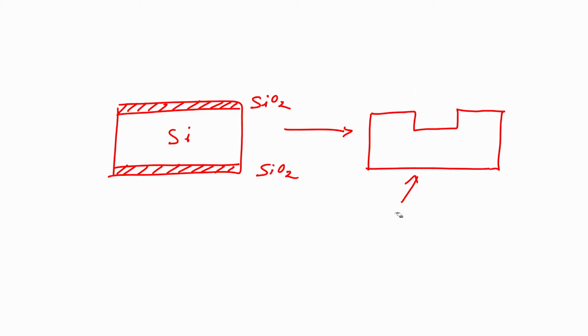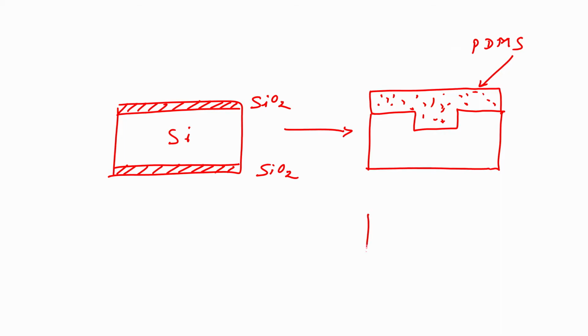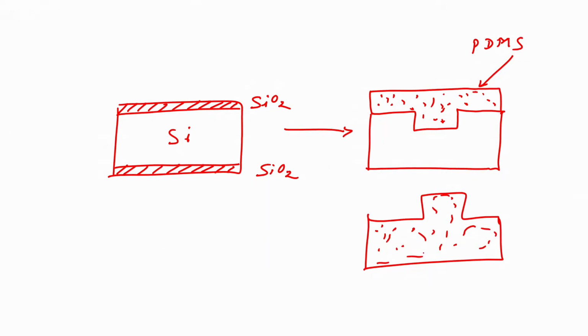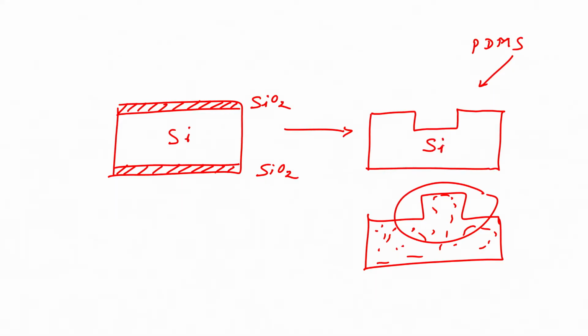So, we will have a mold on which I spin coat or pour PDMS, this is my PDMS, and cure it. After curing, I can strip it off. What will I have? I will have a PDMS structure like this, right. After I strip it off, I can get back my mold, and I have already patterned my PDMS using this particular silicon mold. Again, if I pour, I can cure and I can create another structure.